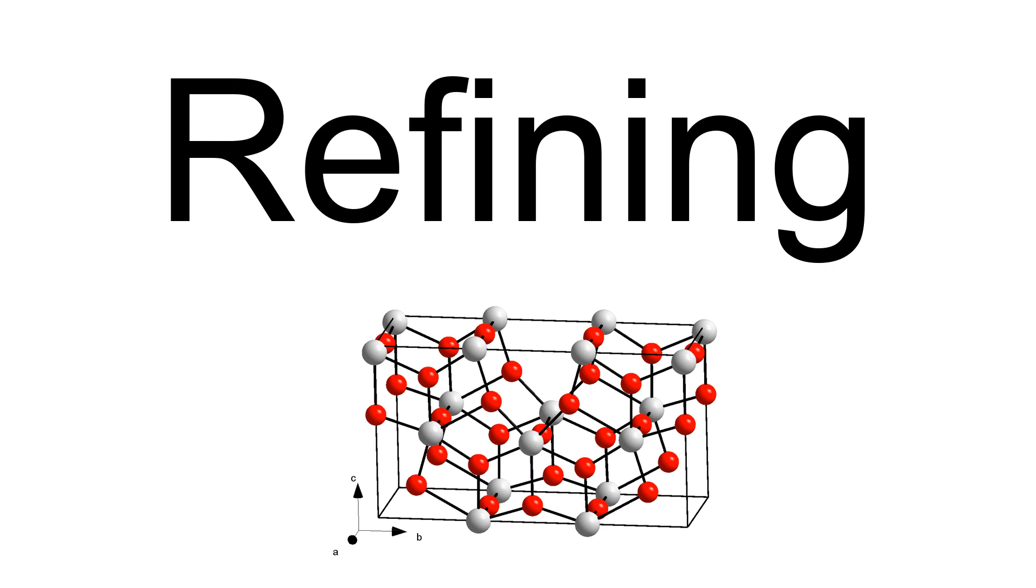The tantalum and niobium hydrogen fluorides are then removed from the aqueous solution by liquid-liquid extraction using organic solvents, such as cyclohexanone or methyl isobutyl ketone. This step allows the simple removal of various metal impurities, e.g. iron and manganese, which remain in the aqueous phase in the form of fluorides.